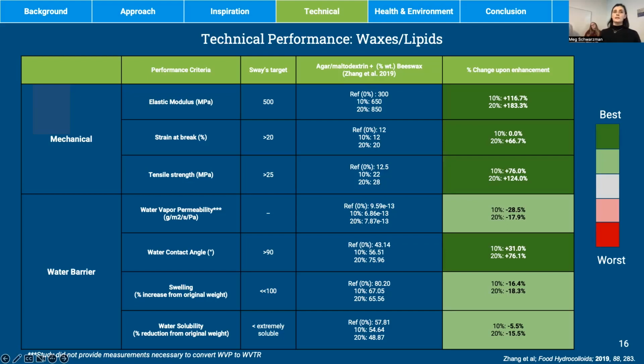However, one thing to note is that the authors did report that the films were pretty irregular and heterogeneous because some phase separation occurred between the nonpolar beeswax and the polar film matrix. However, despite this phase separation, as you can see in this table, there were major enhancements in the properties, or in the performance, of the film for all categories. And especially for the 20% beeswax film, they saw major improvements for all the mechanical properties, as well as for the water contact angle, and then some moderate improvements for the remaining barrier properties.